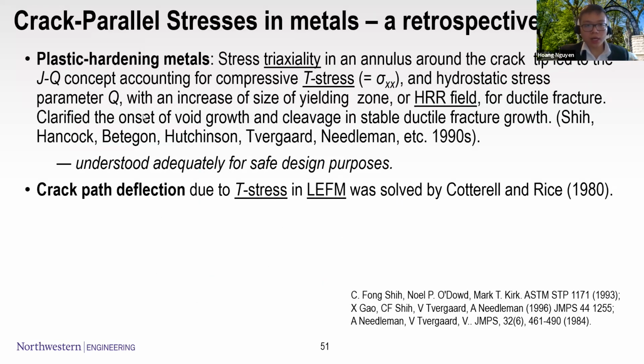So now it's time to see the effect of the crack-parallel stress. As I mentioned, it's different from the quasibrittle materials, where the crack-parallel stress interacts with the fracture process zone. Here it interacts with the yielding zone, and some previous studies have been done. For example, Cotterell and Rice observed the crack path deflection due to the presence of T-stress, but not the change in G_f.